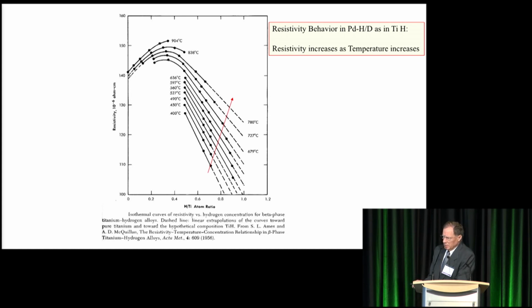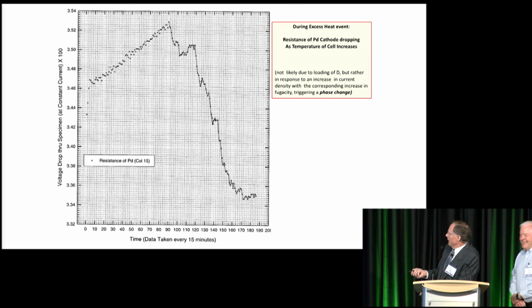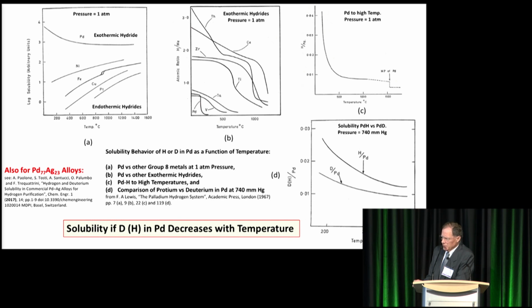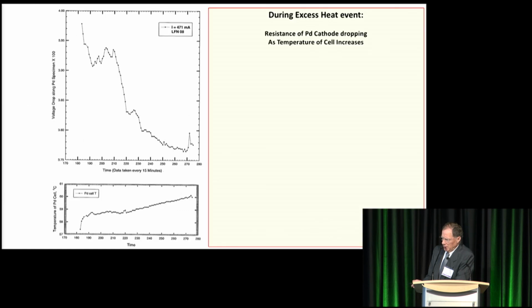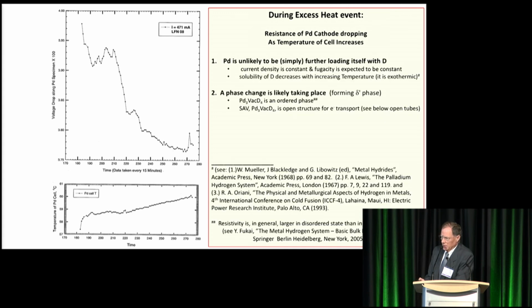I'm going to quickly go through this. I have to get to the end. This is the drop in the resistance during the experiment, and it's unlikely that this drop in resistance is due to loading because the current density was constant, and no, the current density here was increased, which I believe triggered the delta prime phase. Solubility decreases with increasing temperature, so that's another reason why it's unlikely. Here's another event wherein the current was held constant and the temperature was rising. The temperature on the lower scale is rising, whereas the resistance is dropping. So palladium is unlikely to be just simply loading itself, and a phase change is likely.